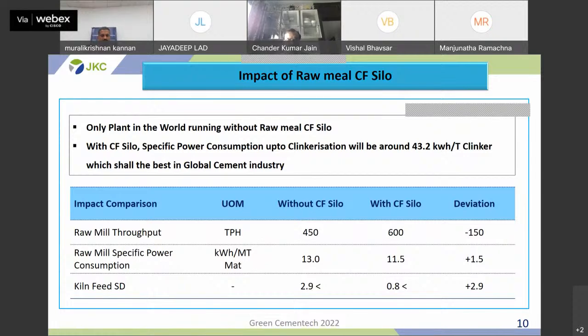JK Cement Muddapur is a standalone plant across the globe which is running without raw meal CF silo with great energy performance. Earlier, our capacity utilization was in the range of 50 to 60%, so we did not go for raw meal CF silo, but nowadays our plant capacity utilization is in the range of 75 to 80%, so we will definitely go for CF silo in the next few years. With CF silo, our specific power consumption up to clinkerization will be around 43.2 units per ton of clinker, which will be globally best. This is just a comparison with CF silo and without CF silo.